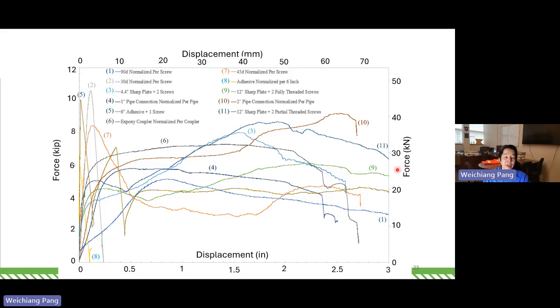So let's look at a few of those. For example, just the screw at 90 degrees. This is the highlighted test for the screw at 90 degrees. The typical signature for this kind of connection is that the initial stiffness is pretty low, not very high, as I mentioned, without any adhesive. And then it's quite ductile. You can see the whole connector is quite ductile for the 90-degree screw here.